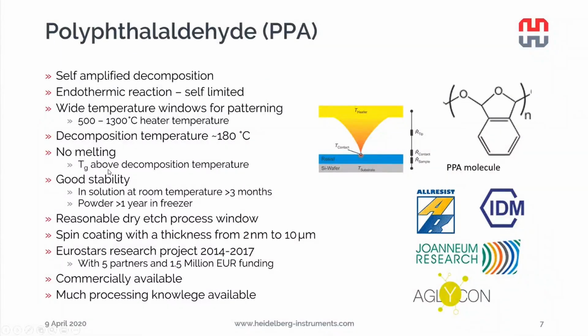The other mentioned properties like the handling and stability are also quite good of PPA. We were able to store solutions for over 3 months at room temperature and still pattern quite nicely on them. We still recommend to store solutions and powder in the freezer, and we have a shelf lifetime of way over a year in the freezer of the powder. We have a quite good dry etch processing window for further post-processing. It's easy to spin coat the sample in a variety of thickness from 2 nanometers up to 10 micrometers.